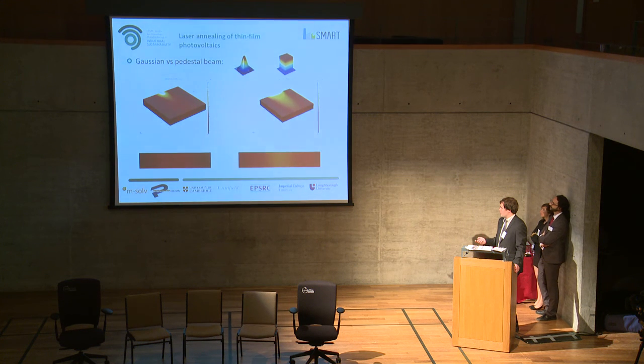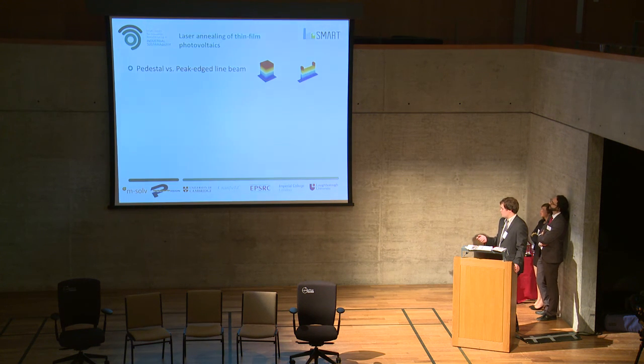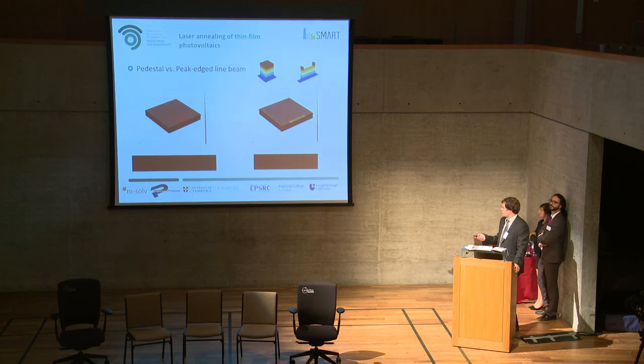And then we can go a step further, and we can compare a pedestal beam versus what's called a peak edge line. So it's much narrower lengthwise. And we put little heat spikes at the edges, which compensate for the additional conduction at the edge, which reduces the curvature. So we get a much flatter, more rectangular heat profile. And that looks like this. The idea of this being to eliminate as much extraneous heating as possible.